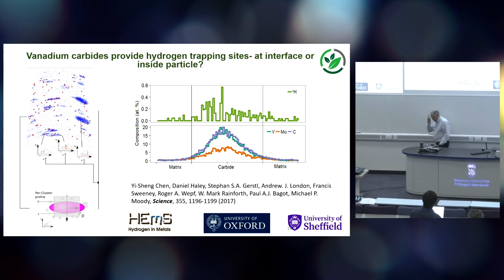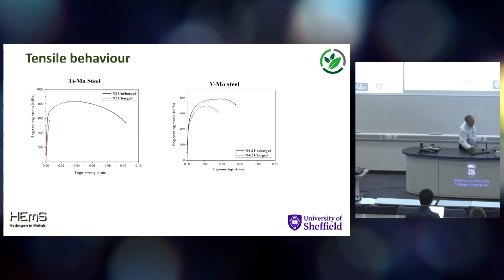The people at Oxford did some absolutely beautiful atom probe work and charged the material with deuterium in this case. And they were able to show that the deuterium, and we believe hydrogen as well, actually goes into the precipitates rather than the classical view that it is trapped at the interface between precipitate and matrix. So you can see here the blue is the vanadium, the red dots are deuterium atoms, and through their modeling they could show here the deuterium was actually located within the precipitate. All the atomistic models suggest it should be the interface between the precipitate and the matrix, but experimentally we see different, so the models are not clearly yet right.